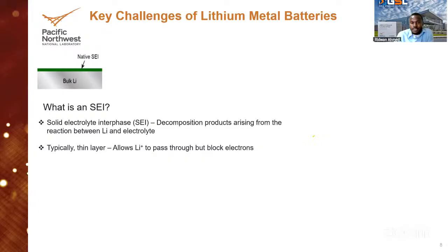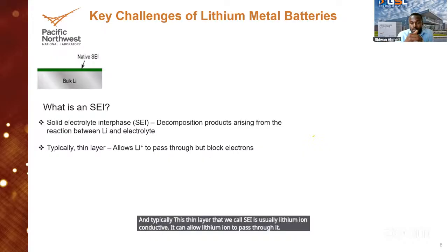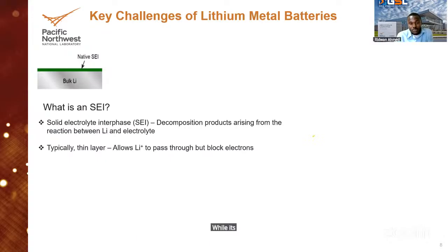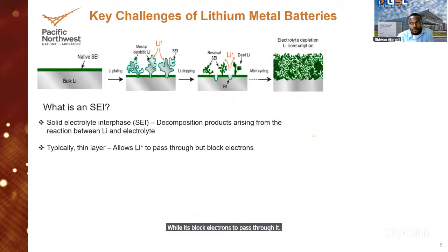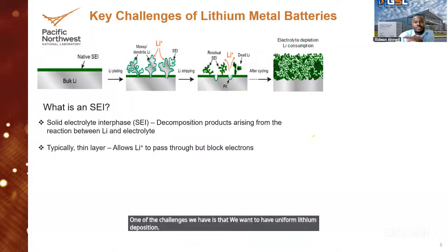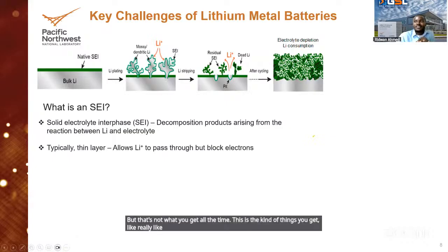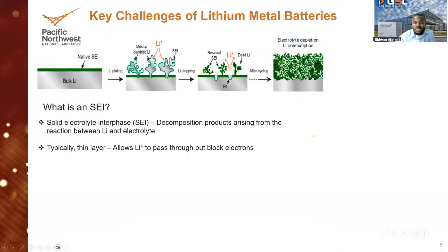And typically, this thin layer that we call SEI is usually lithium-ion conductive. It can allow lithium ions to pass through it, while it blocks electrons from passing through it. So what happens is that when you charge your battery, when you plate the lithium, you add some additional lithium on top of it. One of the challenges is that we want uniform lithium deposition, but that's not what you get all the time. What you get is tree-like growth, and that is called a dendrite. This dendrite is actually not good. You don't want to have it.